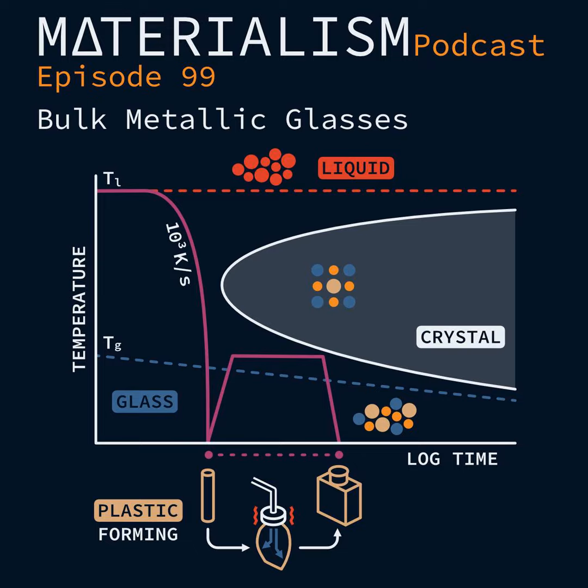And the other ironic thing is they weren't interested in or even thinking about metallic glasses. They wanted to make microstructures with smaller and smaller grains. That was already understood: the smaller the grains in the microstructure, the stronger they become. This is the so-called Hall-Petch relationship. They were envisioning, okay, let's push this to the limit. And they were very surprised. In fact, it took quite a while to convince the scientific community that these are not nanocrystals. These are very different materials. So that was in the 60s.